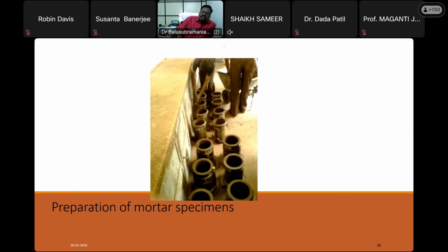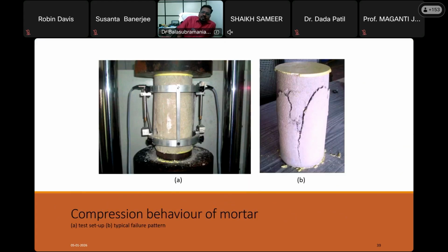So this is the preparation of mortar specimens for compression stress strain behavior, and the experimental setup. Here also you can see this columnar kind of failure. Initially, near the edges, these shear cracks form, and then spall out. The spalling will happen.